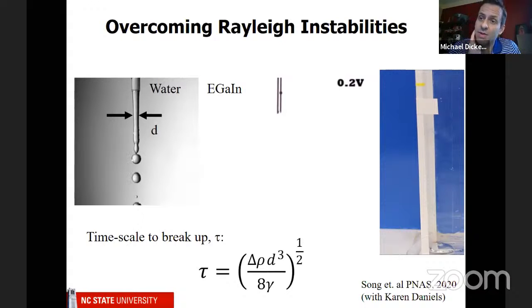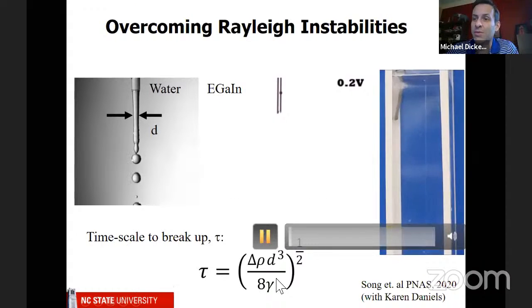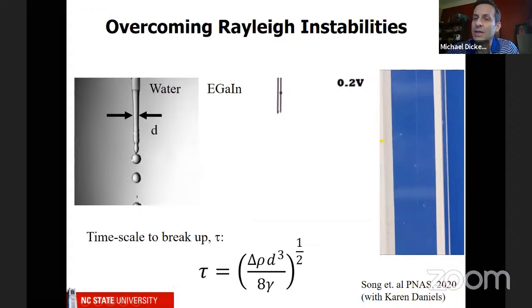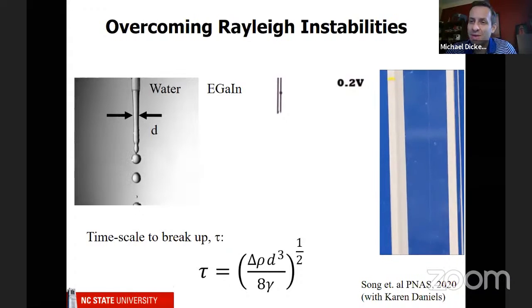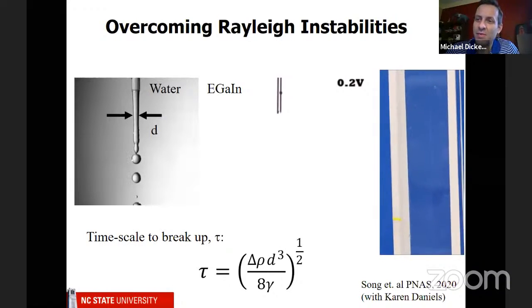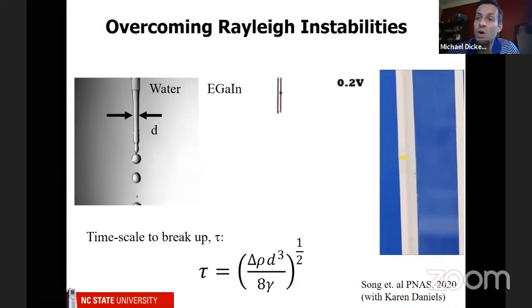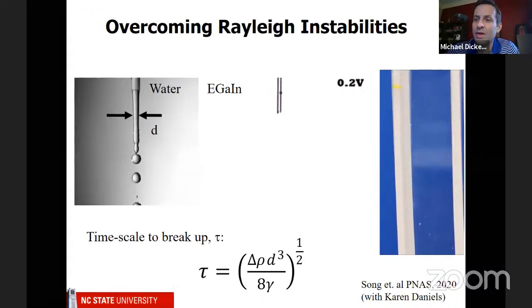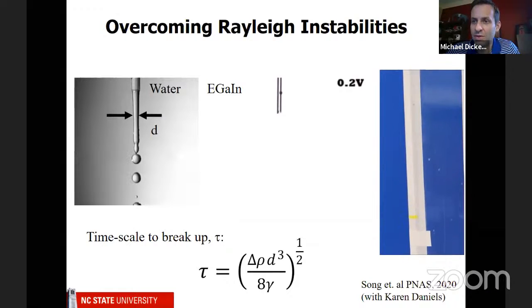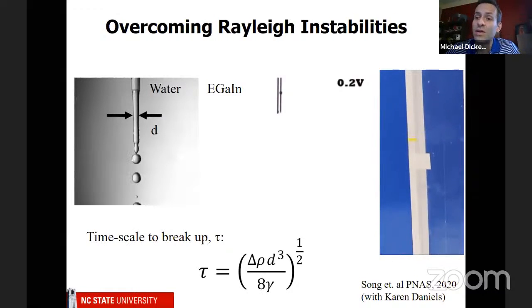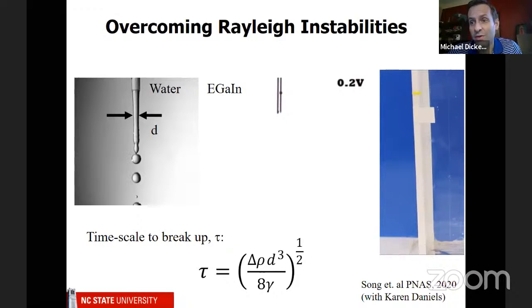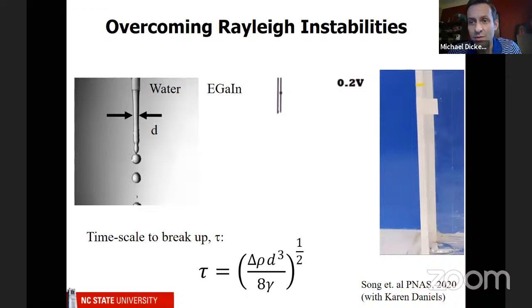But one of the challenges, if you look at this video, for example, is that it actually never becomes unstable. So in terms of studying an instability, if it doesn't happen, it makes it very difficult to study. Now, I think what your question is, is why is it stable? At this point, I can only offer two explanations. One is that the surface tension is just very, very low at that point, and it could even be 0 or negative, which is kind of weird to think about, but that's one thing that works in our favor.